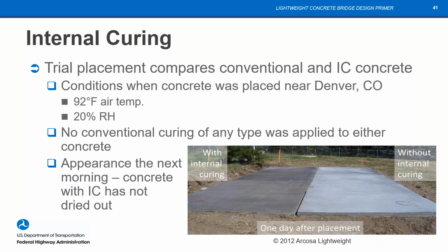Here's a great example of how internal curing works. This is a trial placement for a slab on grade. It represents the floor of a large water reservoir. I mean, it's like a 10 million gallon reservoir or something, very large concrete placement. This is just the trial placement. The concrete on the left has internal curing in it. The concrete on the right does not have internal curing. No conventional curing of any type was applied to either concrete. And this is what they looked like the next morning when they came out and looked at them. So there's no sprayed curing compound or anything on these. Just the internal curing concrete is clearly still moist, while the conventional concrete has dried out at the surface, which makes it more prone to shrinkage cracking and such.